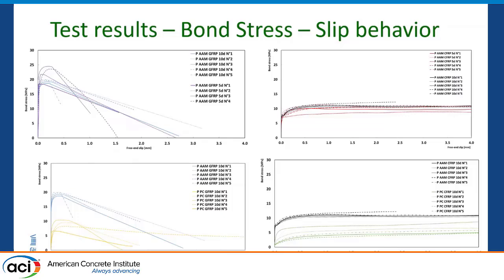Then here we can see the bond stress slip behavior of alkali-activated material with GFRP for 5D and 10D, and we see the sharp increase in the bond strength and then the stabilization on the maximum bond line for both materials. Similarly, it is for the PC mortar with 10D and alkali-activated mortar with 10D, with a clear difference in the maximum bond stress allowed.